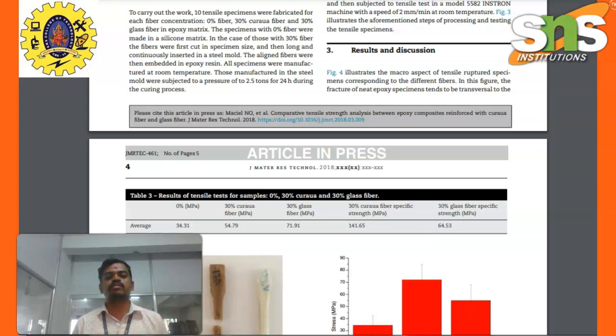All the specimens were manufactured at room temperature. The specimens in the steel mold were subjected to a pressure of 2.0 to 2.5 tons. The curing time is 24 hours.